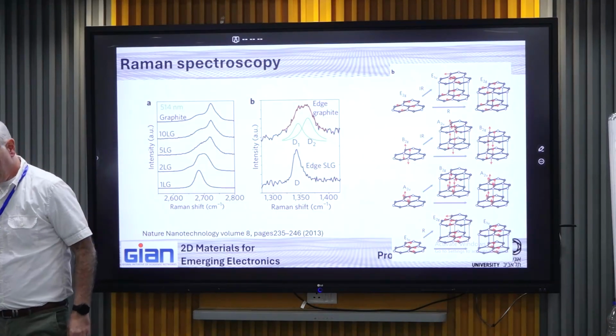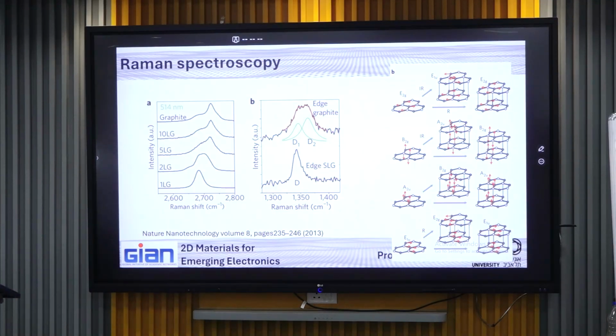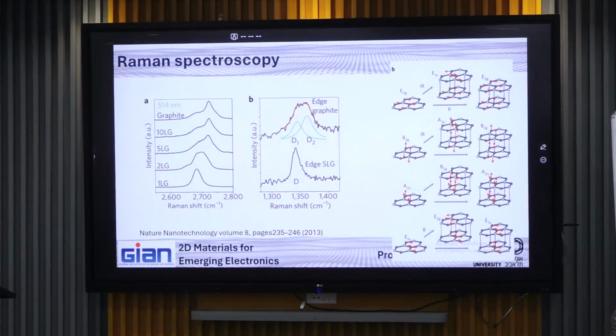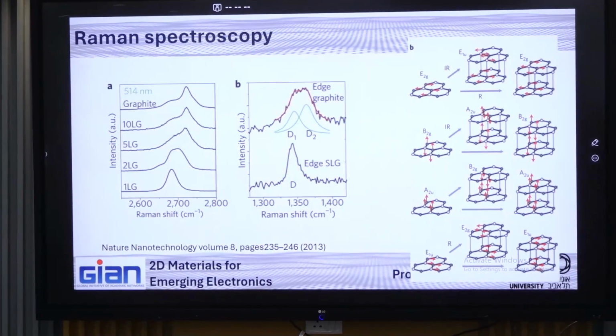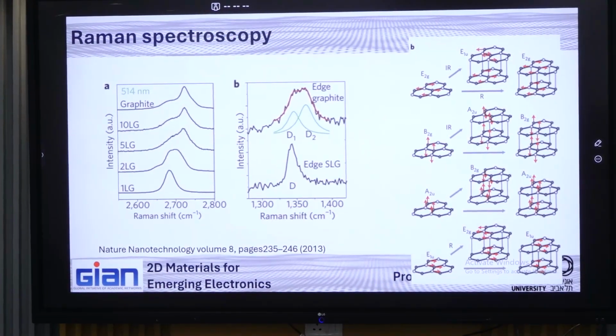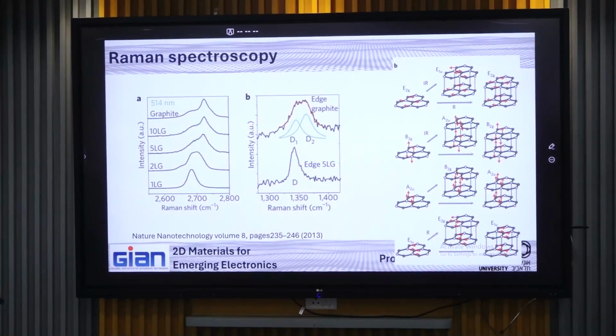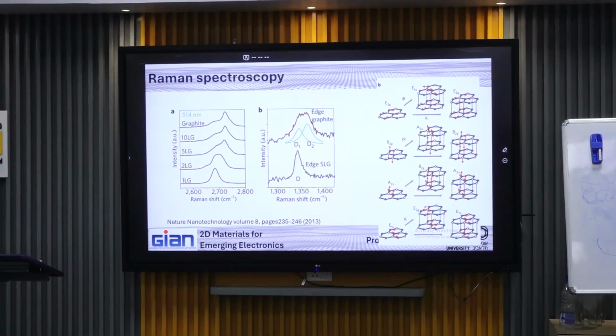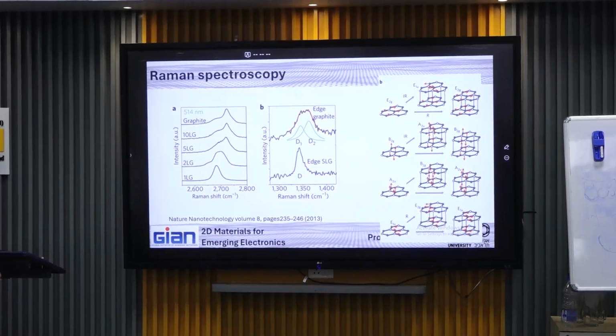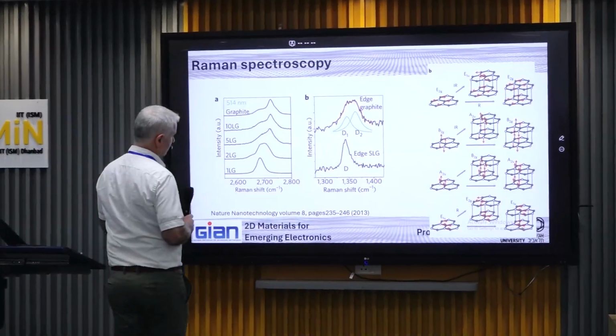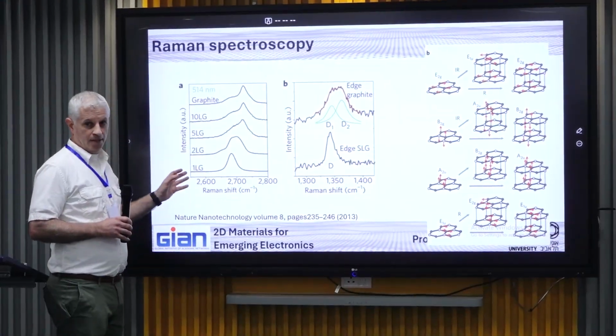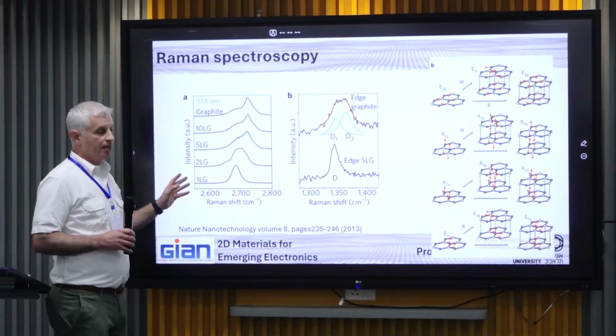And it turns out that, first of all, the cross-section signal of Raman in the graphitic materials, and also in many of the other 2D materials, is very strong, probably because of some covalent bonds. And what you see here is the characterization of the two different peaks that changes dramatically with the thickness, with the number of layers.